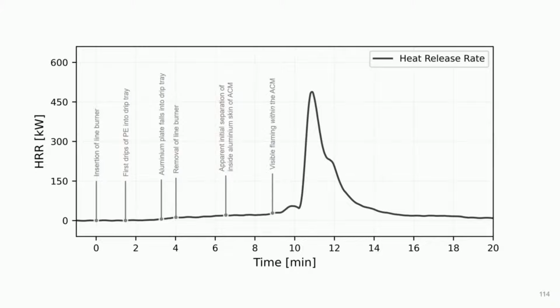We then see visible flaming within the ACM, i.e. between the two aluminium skins of the ACM near its base. We see loss of insulation foil facer just prior to escalation. We then see a jet of flames that appears to be coming out of the top of the ACM itself